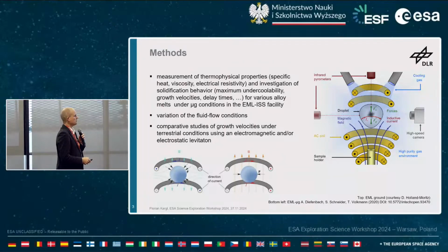Key point is, on ground, you need relatively strong electromagnetic forces in order to lift the sample against gravity. This leads to a deformation of the sample. At the same time, heating and levitation is coupled here. And you also have strong fluid flow inside of the sample on ground. So it makes it difficult for some property measurements. Some measurements are impossible on ground. And for solidification, clearly there's an influence of the strong stirring.